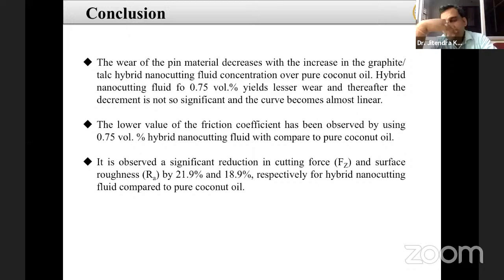And also flank wear I have not measured, but flank wear also obviously, I showed you that same image of the cutting edge. So flank wear also we can measure, and flank wear also reduced. So these are the only two wears that happen on the tool, crater wear and flank wear. The flank wear happens on the flank face and the cutting edge, and crater wear happens on the rake face because of this sliding or sticking and sliding phenomena.